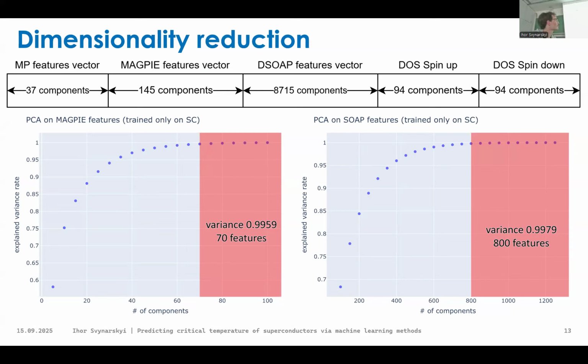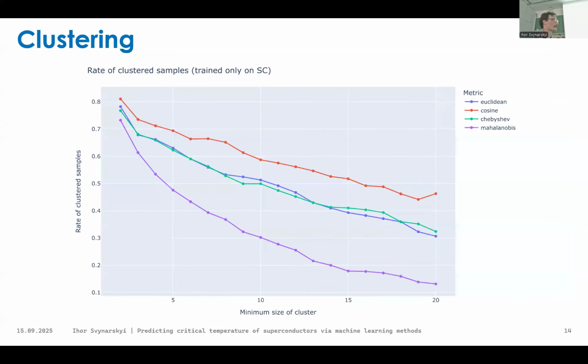Then, having this reduced data set, we tried to do a clustering of superconductors just for fun. And here you can see it was done by, which one? By the HDBSCAN model. So here you can see the minimal size of the cluster, and here the rate of clustered samples. And you can see, if we start to create clusters consisting of only two compounds, even in that case it was unable to cluster all our samples. There are always 20% of the samples unclustered. So clustering is not working on this data set.